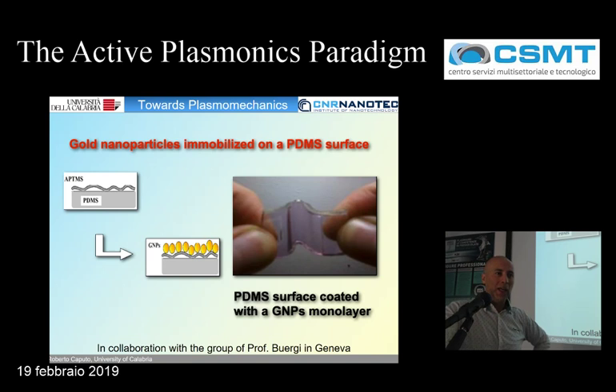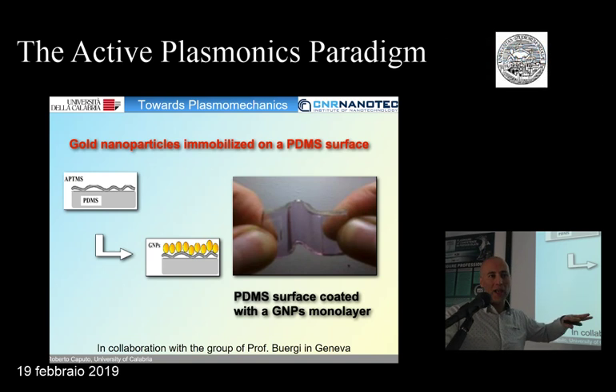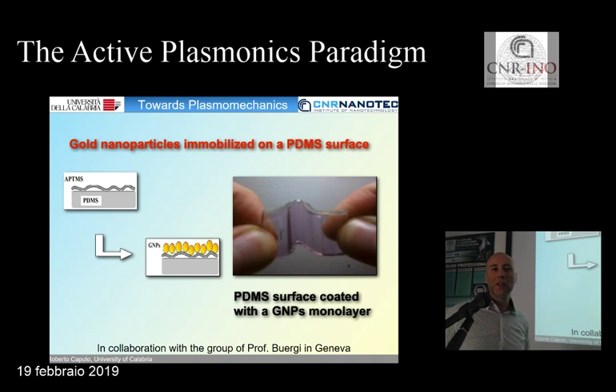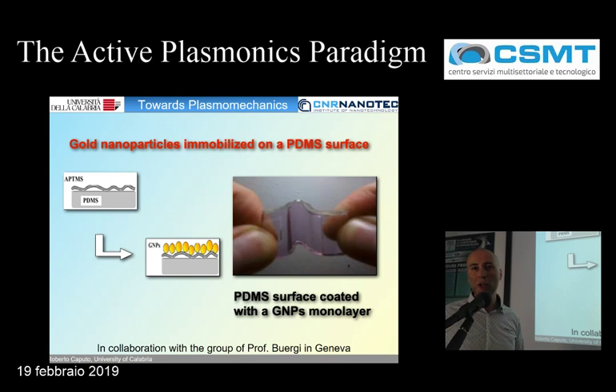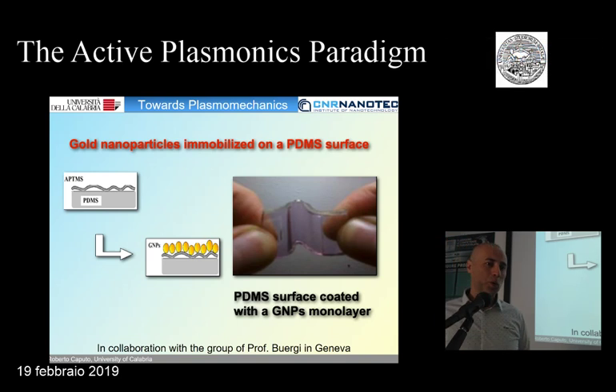So the idea was to use the same distribution of nanoparticles we had on glass, but to make this distribution on a flexible substrate. So we started using PDMS, and we obtained what is represented here. As you can see, the plasmonic color of the material is very well visible, but the particles are just on the surface of the substrate, not in the bulk. And this is some work we made in collaboration with Professor Burgi in Geneva.